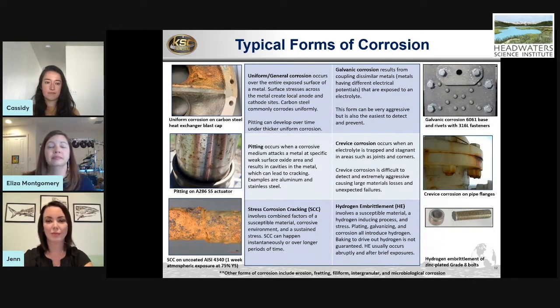Pitting is something that happens often for aluminum and stainless steel. I'm not going to go too far into aluminum and stainless steel in this talk, but that's just how they corrode. And then there are things that normally, if something's under stress, it'll be fine. But if you add a little bit of corrosive environment, it'll immediately crack and break. And that is a huge problem. So we have to care about that, because with some aerospace alloys, you can't have it crack when it's in space, right? That's extremely scary. There are people who dedicate all their life to worrying about something fracturing, and stress corrosion cracking is part of that. And I have to kind of pop in when that's an issue.